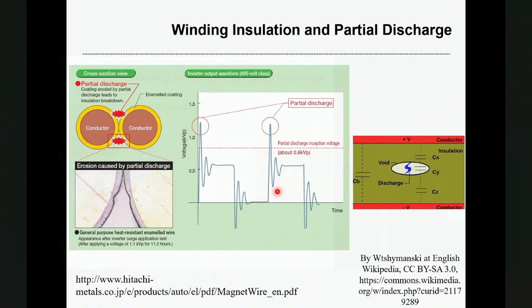So this overvoltage will cause the winding insulation degradation through the partial discharge effect. Basically, if the voltage is higher than the partial discharge inception voltage, it will trigger a partial discharge. And this partial discharge effect will eat up some of the insulation material, and over time, it will cause the insulation breakdown.